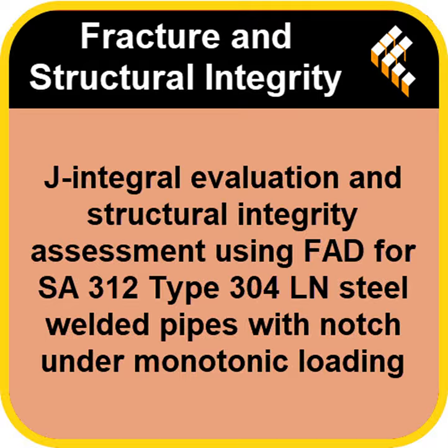So if the pipe material is really ductile and it stretches and deforms a lot, absorbing energy before the crack actually spreads significantly, the load-CMOD method captures that whole energy absorption process. Exactly. It's measuring the total energy being absorbed by the component as it deforms plastically near the crack. Because it includes that plastic energy contribution, it tended to yield slightly higher effective J integral values. This suggested slightly higher actual fracture resistance in the component test compared to just the baseline material property. Which means the calculated KR ratio would be slightly lower.